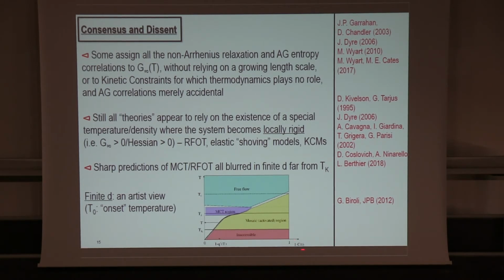Actually, it's 1 minus the correlation function. So when the correlation function is 1, effective time is 0, and when the correlation function is 0, time is infinity, but this effective time is 1. And the y-axis is temperature. And so the idea is that there are different regimes here. So there's this dynamical transition, this MCT transition, which is only going to govern, in any case, the short time regime. In the long time regime, we know that barriers don't grow to infinity, so there's going to be barrier crossing. So at long times, the dynamics has to be governed by barriers and by activation anyway.